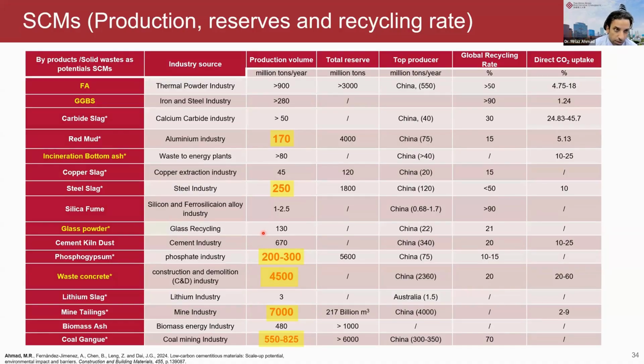But the other industries, such as the carbide slag byproduct, this calcium, it provides us calcium hydroxide. But if we want to look at the commercial calcium hydroxide, it is extremely carbon intensive. For 1 kg, it produces 1 kg of carbon dioxide emission. But this carbide slag, again, is very useful. So I think it can vary from byproduct to byproduct. But in general, I think in most cases it will reduce the carbon emission. Yeah, it will lead to a green product.